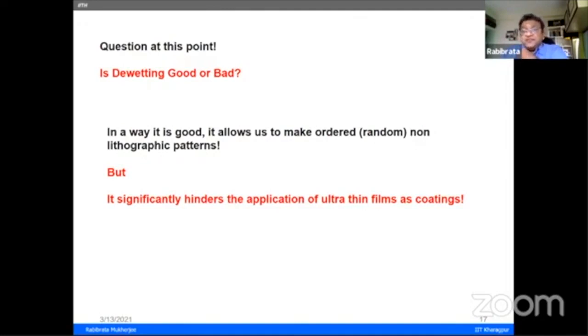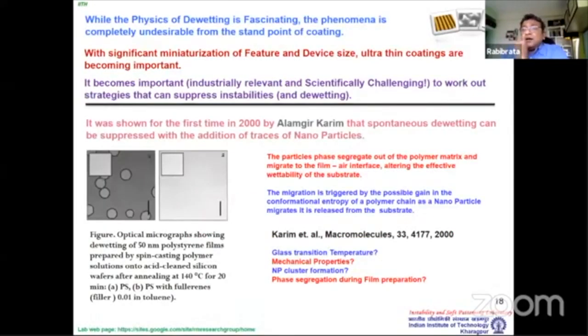One of the things is to functionalize the surface, modify the polymers, cross-link them, etc., which are all difficult to scale. So one beautiful technique that Manisha's former boss, Alamgir Karim, and his group came up with way back in 2000, again another absolutely stunning and almost topic-defining paper, I would say, is to add nanoparticles. The first work was done with fullerene, in trace amount added to a dewetting film, and they could show that a film which would otherwise dewet, above a critical concentration of the nanoparticles, which is very, very low, like 1% weight by weight, becomes completely stable. I would like the audience to take note of a particular phrase: above a critical concentration. Above a critical concentration of the nanoparticles, the film becomes stable.